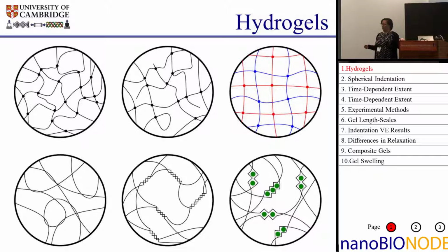And on the right, you have alginate, which is when you have the cross-linking due to a divalent ion, like a calcium ion, where the calcium ion actually grabs onto two chains and you get little local interactions. And it can be multiple interactions like shown there with 2 or 3 individual points.